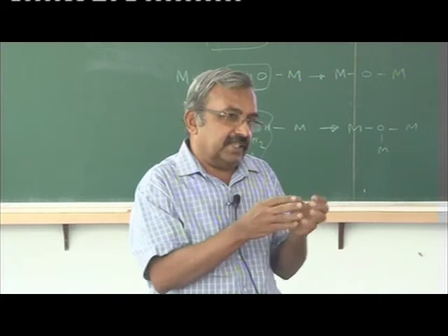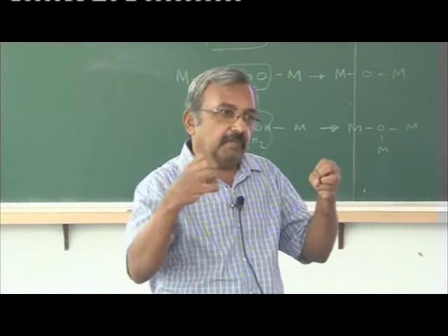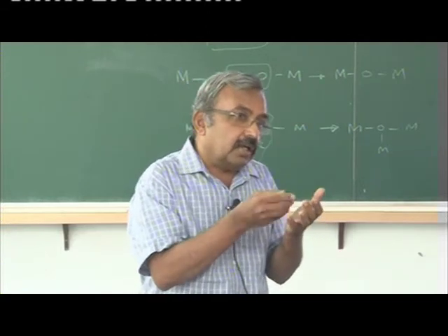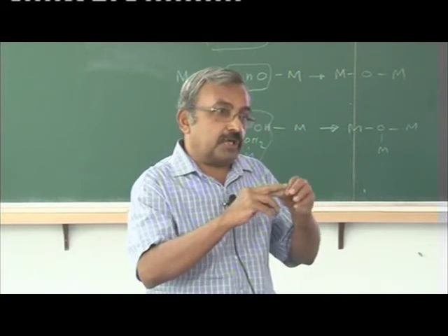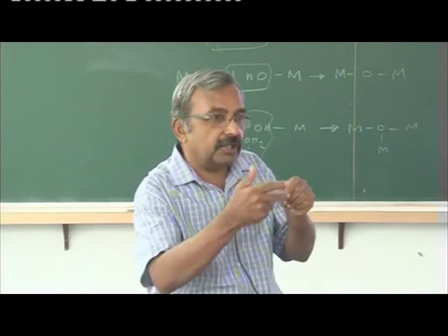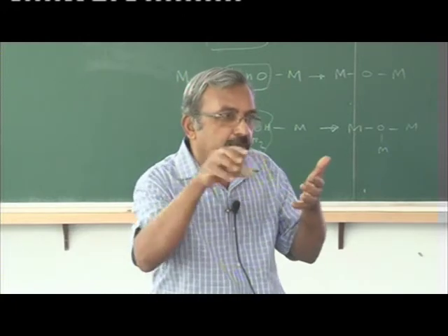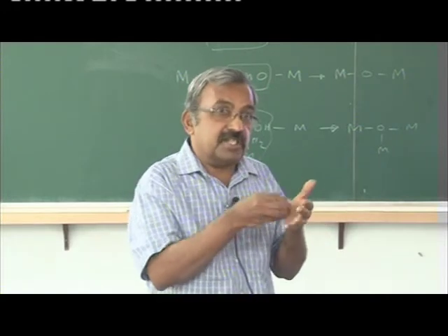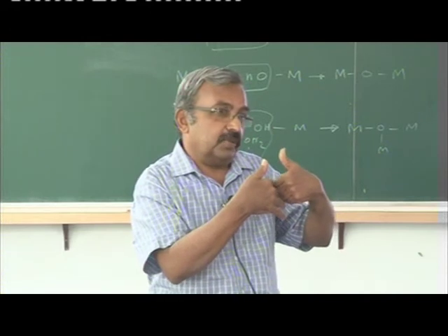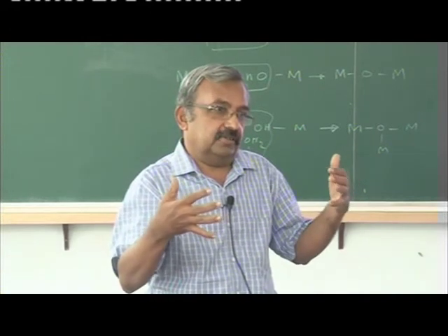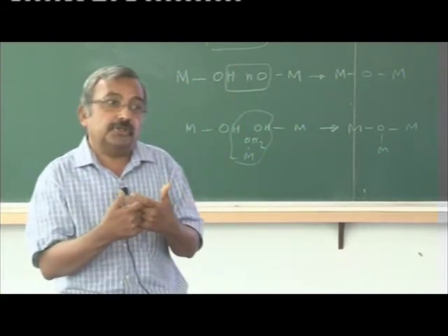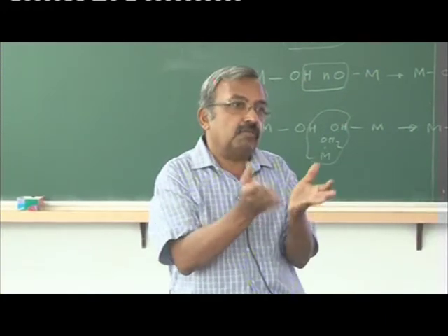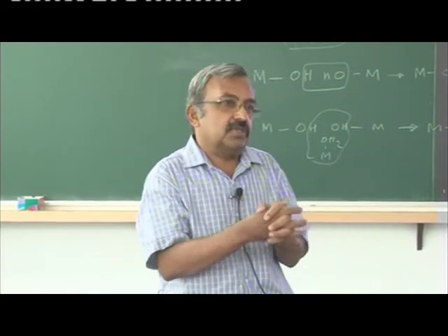So now what happens is, in our case, it is the Anderson cluster combining with a copper complex. Whether the copper complex is a copper hydrate or copper pyrazole, copper pyrazole also can have different complexing species, right? 1, 2, 3, 4. After all, you can write the equilibrium with copper 1 pyrazole, copper 2 pyrazole, copper 4 pyrazole. In few cases, we have seen copper 2 pyrazole also coming into the picture. So it becomes complicated. You understand? So this is where the polyoxometalates are nice, but at the same time they are difficult because the number of species involved in the self-assembly process are too many.